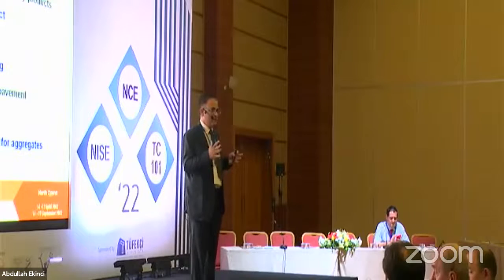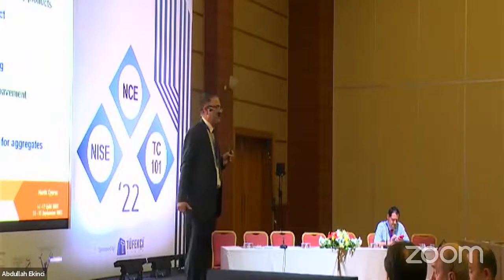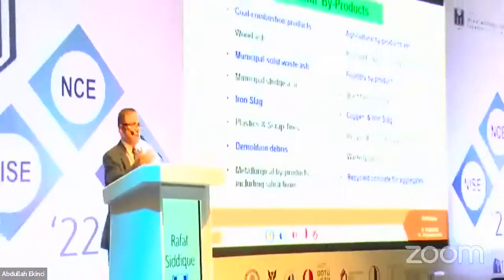Even if I say the strength has come down to 10 megapascal, 15 megapascal or 20 megapascal, that still is useful. The reason is we have a misconception that when we talk of concrete, our mindset only goes to structural concrete, the concrete which you are going to use in a high-rise building. Like in India, we use minimum 20 megapascal concrete. I don't know what it is in Cyprus, maybe minimum 20 or 25 megapascal. But the concrete which you use for making paving blocks, like when you walk to a restaurant, you have paving blocks. That doesn't require 20 or 25 megapascal. Even if the concrete strength is low, 10-15 megapascal, we are able to utilize the byproducts. You should not worry about how much reduction. The focus is where we can use that concrete.